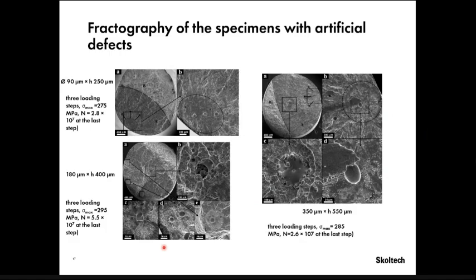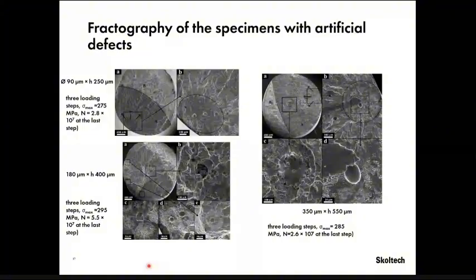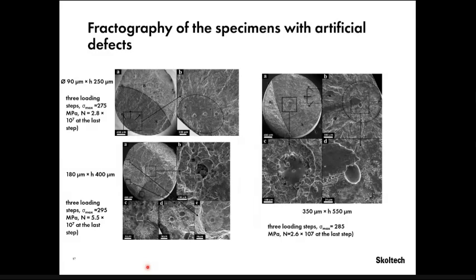We didn't come across it before in the literature, that we have at the same time like 3 fine granular areas, so FGA, at 3 sites of the crack growth. For conventional materials, we didn't find that. For additive manufacturing, it's probably not so, it's already studied quite well, but still we didn't see such results. We relate it to the fact that additively manufactured materials just have many more defects in general, and that's why the probability of crack origination at different sites is higher.